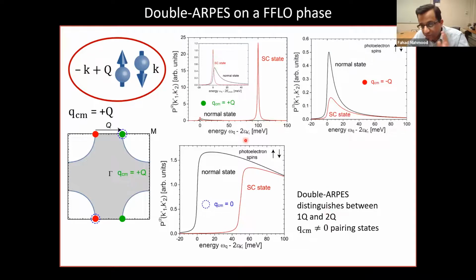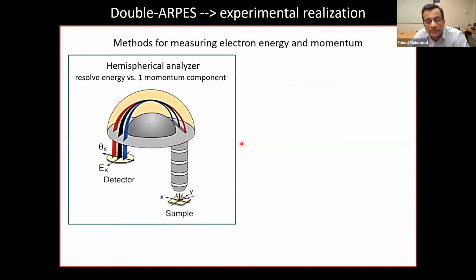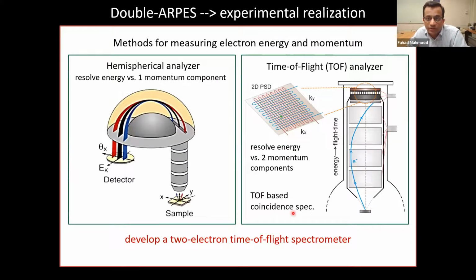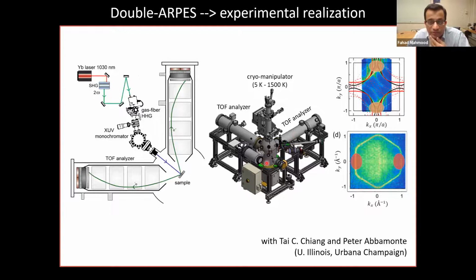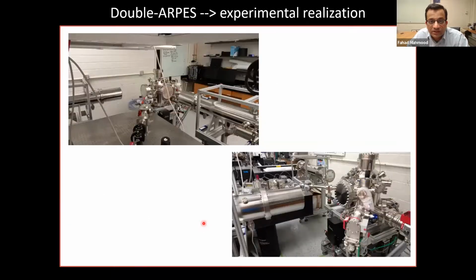So I'm just going to say this is also the FFLO phase. We can get similar results there. I just want to briefly flash that we are very close to experimentally implementing this. I'm an experimentalist, so that was all sort of theoretical results. But we're basically going to be using two time-of-flight analyzers to perform this double-ARPES measurement as a function of temperature. So essentially probing different parts of the Fermi surface. And just two weeks ago, the analyzers were delivered in our lab. And so this is the actual analyzers being set up right now.